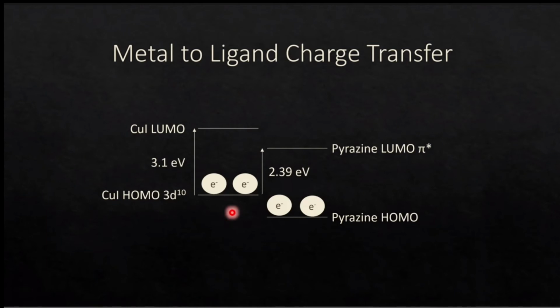But what happens whenever you bind copper iodide and pyrazine is that through that coordinate bond, these electrons can now access the LUMO of pyrazine, which is only 2.39 electron volts away. And so the electron can jump up to the LUMO of the pyrazine and then jump back down into the HOMO of the copper iodide and release those 2.39 electron volts as a photon of light. And when we see that, that looks yellow. And so this explains why the color of the compound changes.